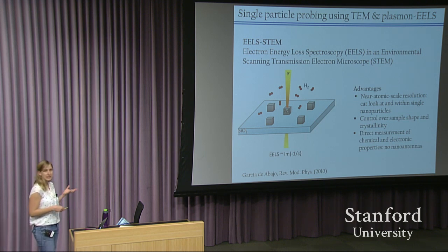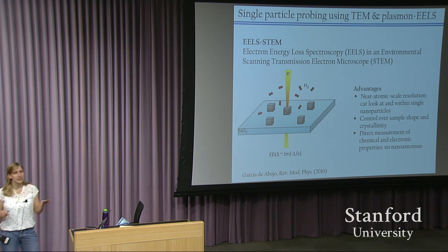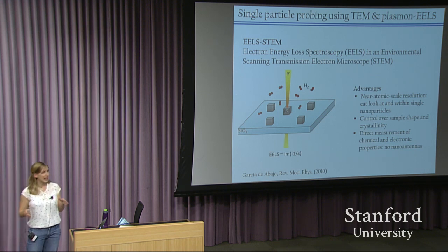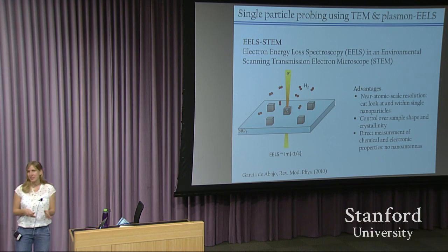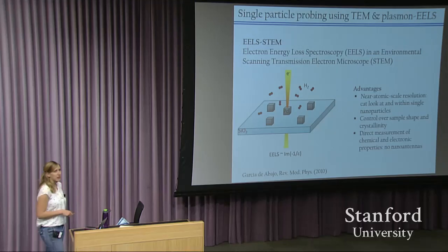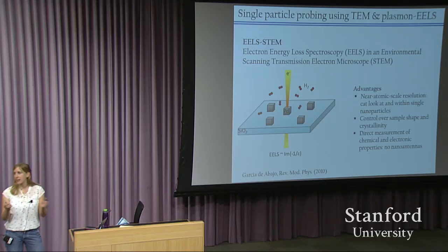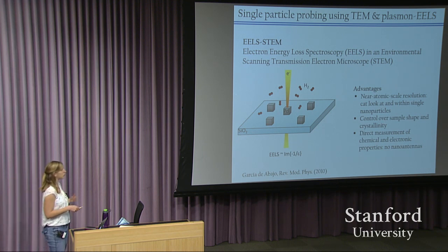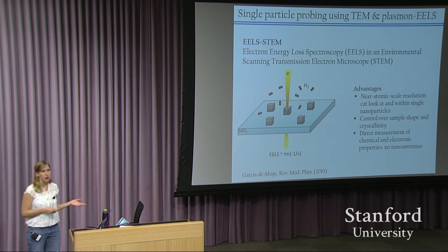Also, since we're colloidally synthesizing our nanoparticles, we have control over the sample shape and the crystallinity. So we can synthesize a variety of shapes and sizes and crystallinities and then look exactly at the thermodynamics of a single nanoparticle and figure out which ones might be best to maximize this energy storage capacity. And then finally, unlike many of the other single particle measurements out there that rely on nano antennas to transduce the signal to the far field, this is a direct measurement of the chemical and electronic properties. We don't need any nearby nano antennas that may otherwise influence the thermodynamics or kinetics.